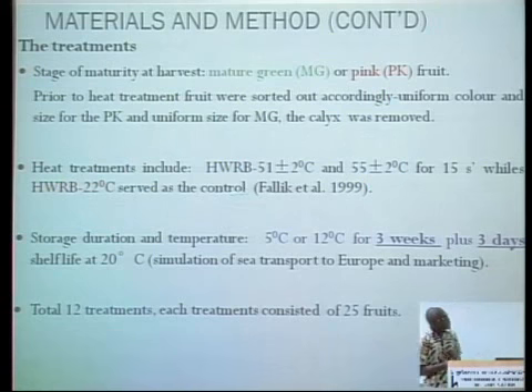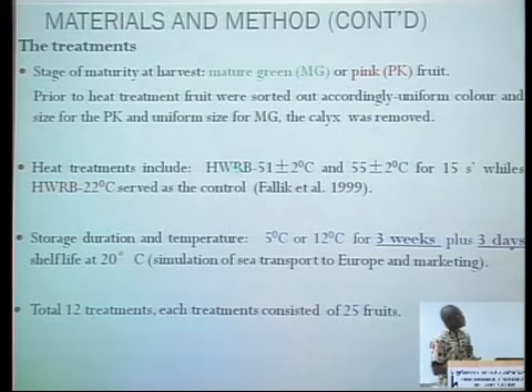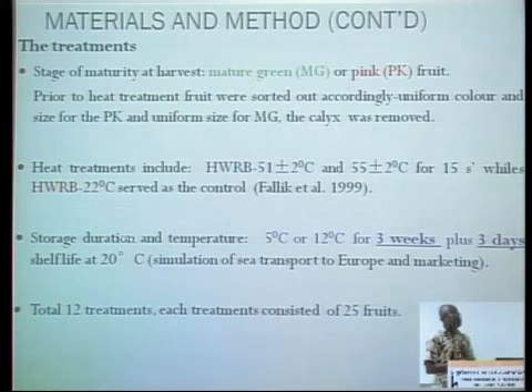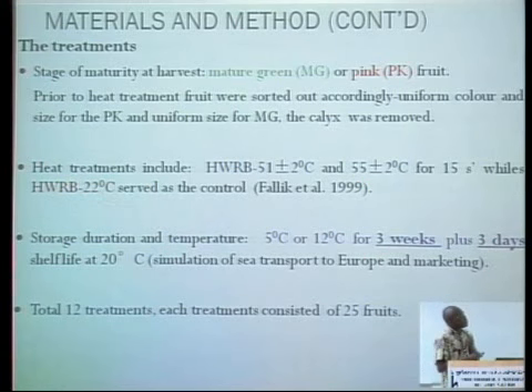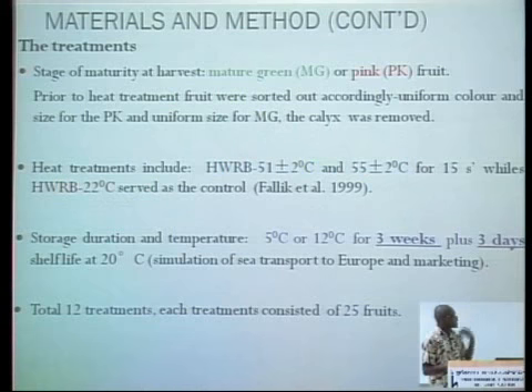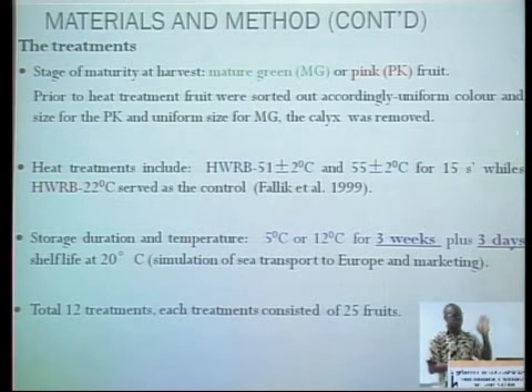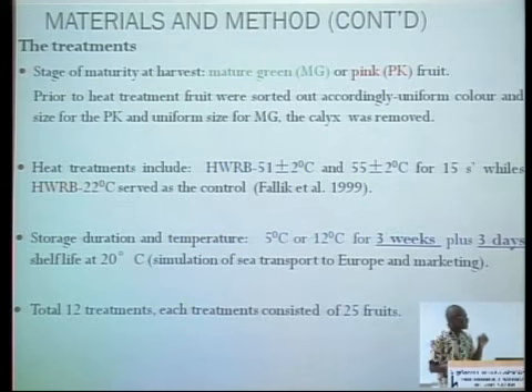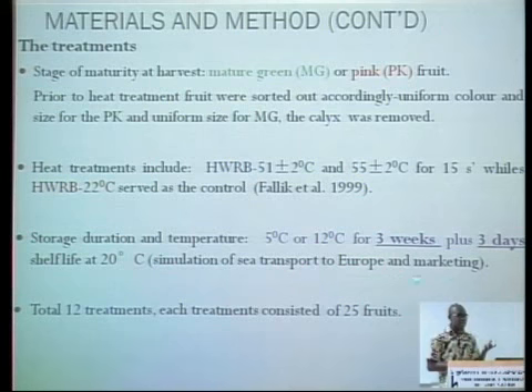Now, the temperatures that we used for our treatment: we washed the fruit at 51 and at 55 degrees for 15 seconds, whilst 22 served as our control. 22 is the temperature mostly for tap water. So we wanted to see, if we use tap water in relation to the heat treatment, what would be the effect. Then after the heat treatment, the fruit were stored at 2 separate temperatures, for both pink and mature green: 5 degrees centigrade and 12 degrees centigrade for 3 weeks, plus 3 days of shelf life. The emphasis of this was a simulation of sea transport to Europe and marketing. So in total, we had 12 treatments, and each treatment consisted of 25 fruits.